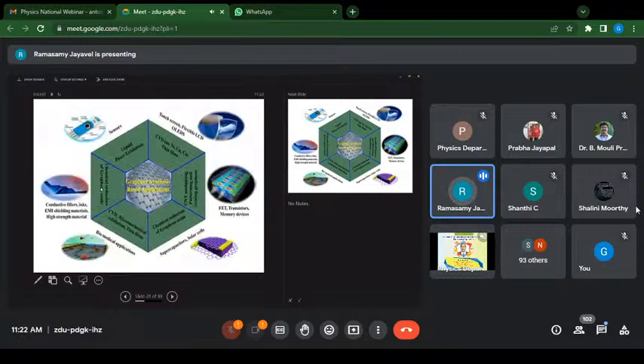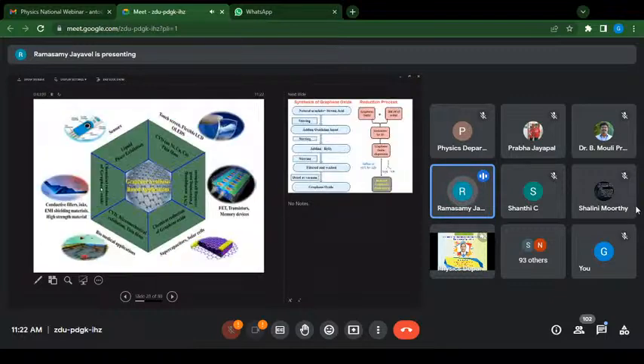And the other advantage is that the synthesis method can also be based on the requirement or the application for which we are making the material. For example, if you want to use it for flexible applications or touch screens, the best way would be CVD, conventional chemical vapor deposition technique. And if you want to use it for FET transistors, then patterning of the CNT surface or graphene, etching the graphene surface is the most appropriate technique.